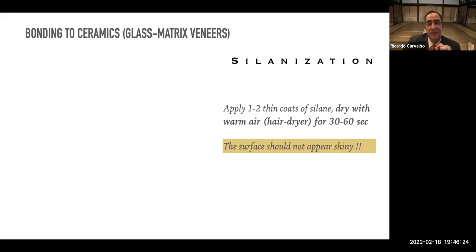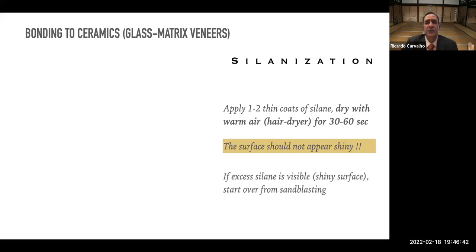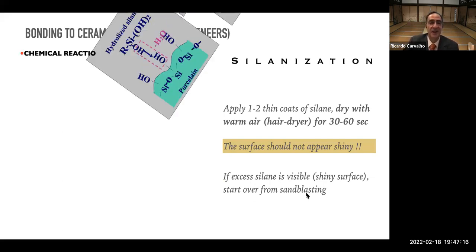And that's a kind of critical point because everybody is used to applying adhesive to enamel and dentin. And after you apply your adhesive, your surface should appear shiny. You should be able to see that the adhesive is applied over there. But the silane is the opposite. With silane, if there is a shiny surface, that is a clinical indication that you probably applied way too much silane. And as we're going to see, excess silane is a big problem for bonding. So if you do see a shiny surface after you apply your silane, that's probably an indication that you applied too much and you should start over from sandblasting, and then hydrofluoric acid and silanization again.